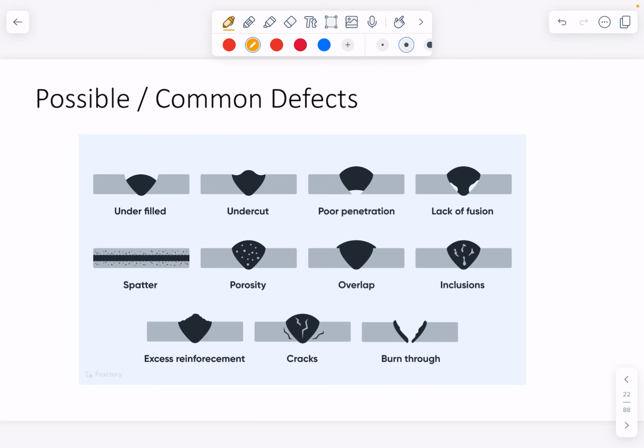There are a lot of possible or common defects. If you've got a really good welder, trade qualified and very experienced, they will lay a beautiful weld down every time without even thinking about it. If you or I pick up a welder, we're likely to do every single one of these errors. Porosity is a common one. If you're using a MIG welder and you forget to turn your gas on, you'll start welding and you'll get a real bubbly weld pool where it runs out of gas, which you've then got to go back and grind out and weld back over.